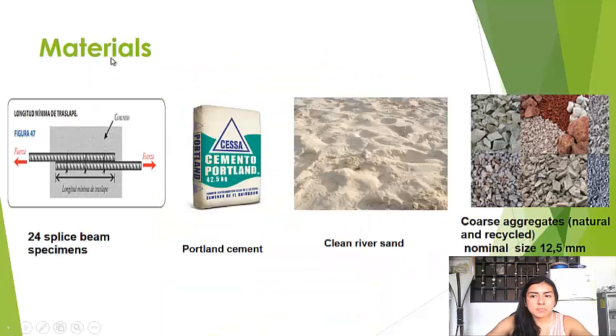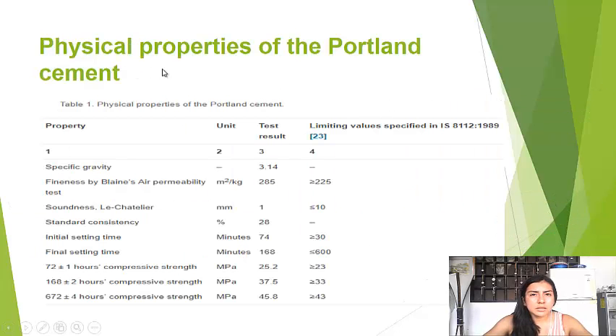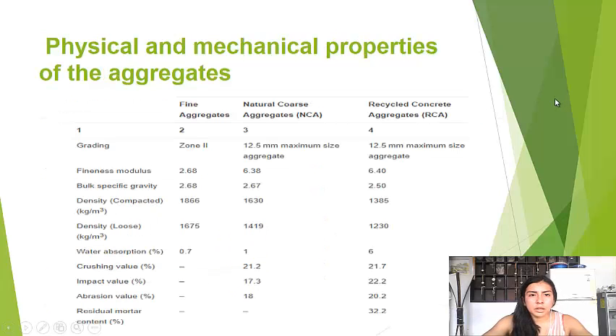The following materials are used in this investigation: 24 splice beam specimens, Portland cement, clean river sand, and coarse aggregate, natural and recycled, with a nominal size of 12.5 millimeters. This table presents physical properties of Portland cement, for example, specific gravity, fineness by Blaine, soundness by Le Chatelier, and standard consistency. This table presents physical and mechanical properties of aggregate, natural coarse aggregate and recycled concrete aggregate, with properties like fineness modulus, bulk specific gravity, and density.